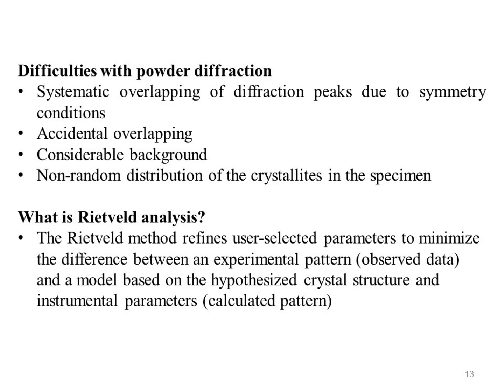What is Rietveld analysis? The Rietveld method refines user-selected parameters to minimize the difference between an experimental pattern, meaning observed data, and a model based on the hypothesized crystal structure and instrumental parameters, meaning calculated pattern. Full profile fitting using crystallographic constraints, lattice parameters, and space group to constrain peak position, crystal structure to constrain peak intensities.